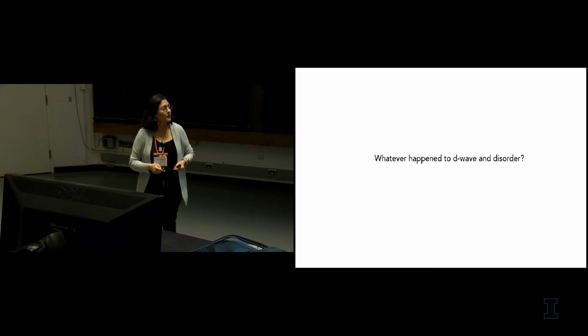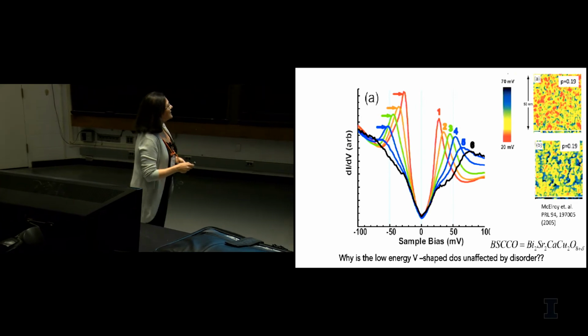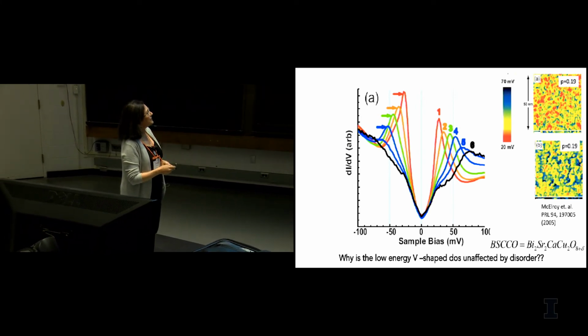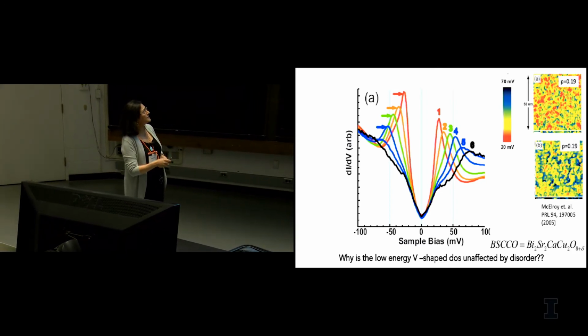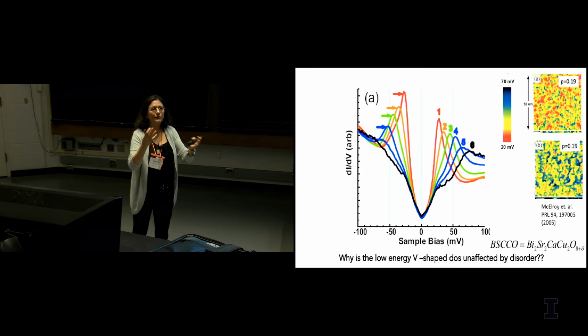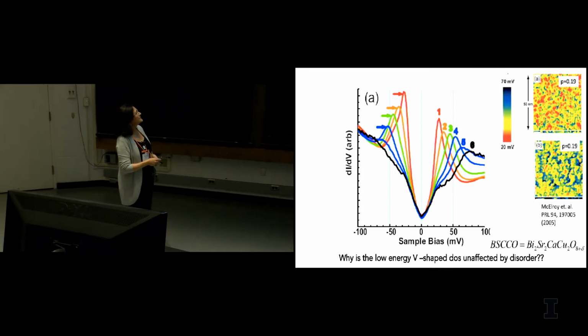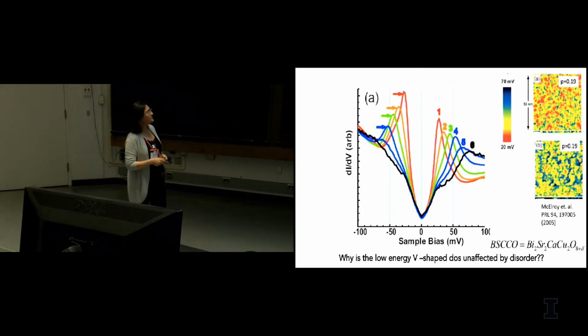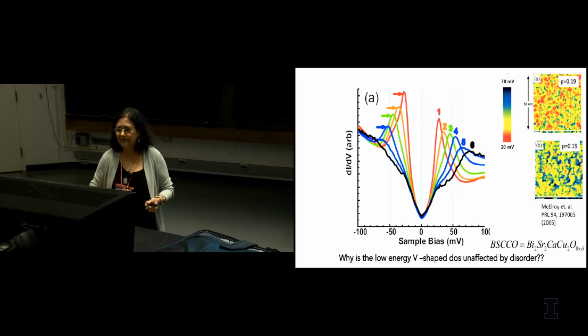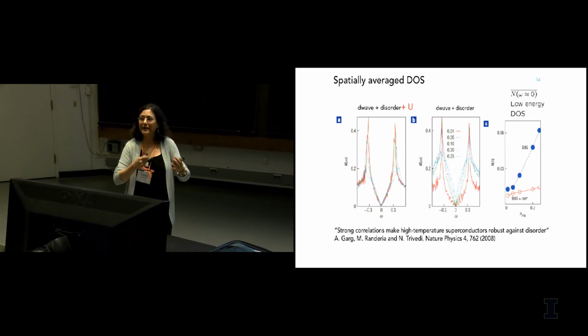So, coming back to my original question, whatever happened to the D wave and disorder? A very short digression here just to say that there was some very beautiful data from Seamus Davis's group that showed that when they made these samples with different dopings and looked at different regions, the behavior at high energies, so this is dI/dV, the density of states versus the bias, there were big differences depending on whether you were in a red region or a black region and so on. These should have been 0.19 and some other doping. This is some typo here. But in any case, it's not important. It just says when you went to different dopings, the fraction of red and black regions changed, but the spectra in these regions were very similar. And what you want to take away from this is that the low energy V-shaped density of states remained unaffected by the disorder.